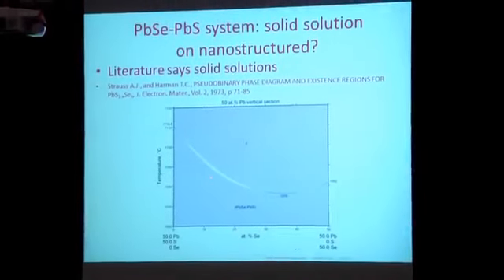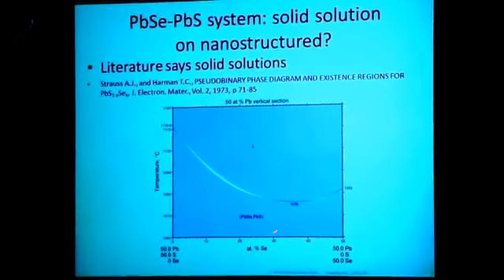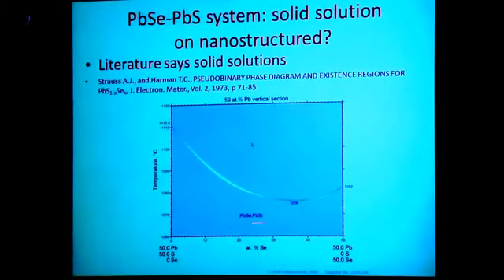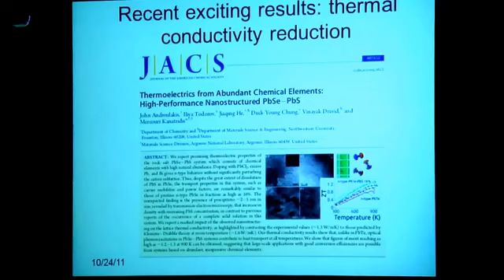But we found in the literature there was a phase diagram, and we found papers that said actually this particular system does form a solid solution. There is no phase separation between them. You see it here. There's no nucleation and growth region. There's no spinodal decomposition. So this was a legitimate solid solution. However, we nevertheless did it anyway. And we were surprised to see that, in fact, lead sulfide, lead selenide, it's not. It's an inhomogeneous system. In fact, we found all kinds of nanostructures. Nobody had bothered to look before.